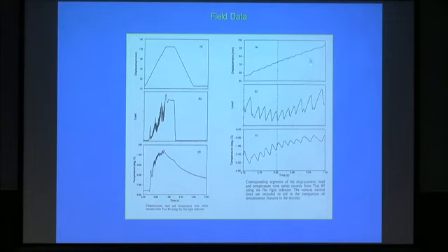So if you look at the expanded views of these three records, you see the stepwise motion. You see the steps associated. The line I put here shows the synchronization between the types of events. So when the indentation is fast during a load drop, you see it here. And corresponding to that, the temperature would have a bump up at the time when those spalling events happen.